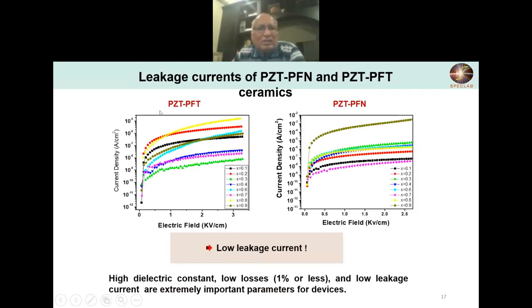Coming to the losses, these leakage currents. So we can see that these materials have very low leakage currents. We're talking about 10 power minus 10, 10 power minus 9, 10 power minus 8 in this region. And the same is true for PZT, PFN. So this is another very interesting thing. We really need high dielectric constant, low losses, and also low leakage current, which are extremely important parameters for device fabrication. So we consider that these materials are indeed very good for that.